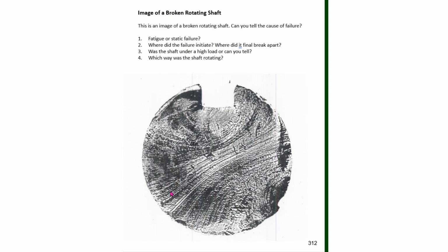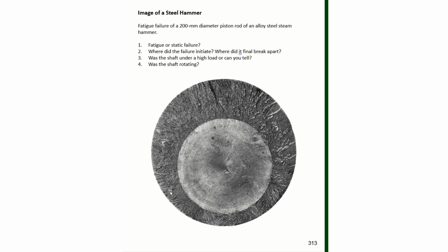Now let's look at a little different scenario. This is the image of a steel hammer where we have an impact load, but it's not a cyclic rotating shaft. And what we have here is, here you can see a very smooth surface, and then here we have the brittle fracture. So if you remember from your 250 experiment where you pulled the tensile specimen apart, you had a very rough, jagged surface. And that's the kind of surface that you get here where we have a brittle fracture.